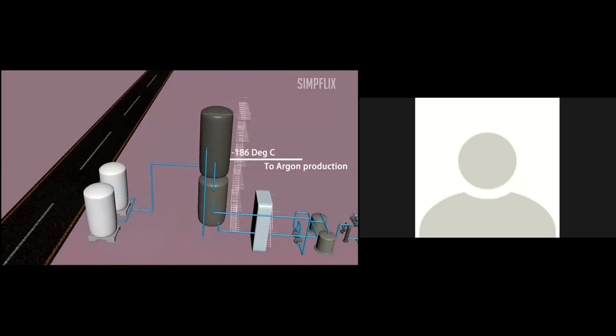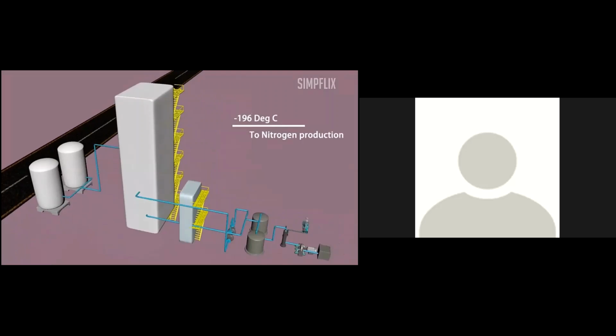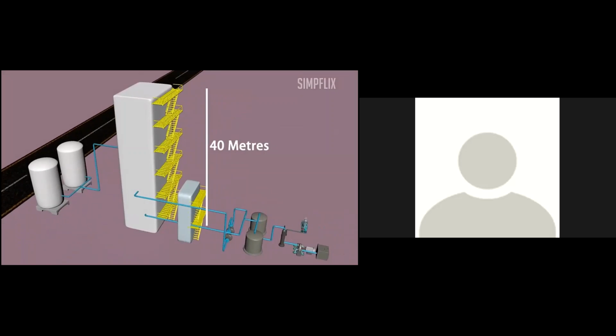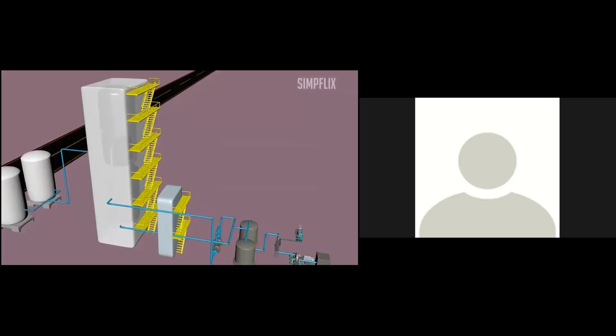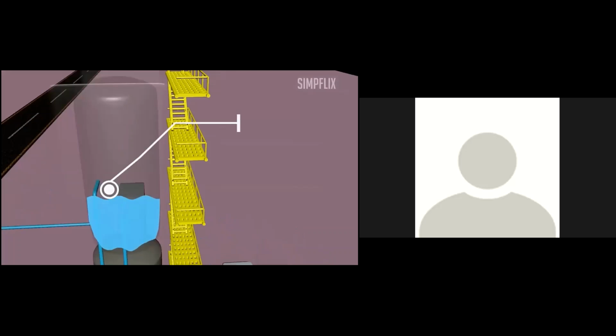Argon is collected at the -186 degrees Celsius area. The top temperature is at -196 degrees Celsius and nitrogen is collected. Normally, height of this distillation column will be around 40 meters, depending on the production capacity of the oxygen plant. Oxygen produced using this technology will be having a purity of